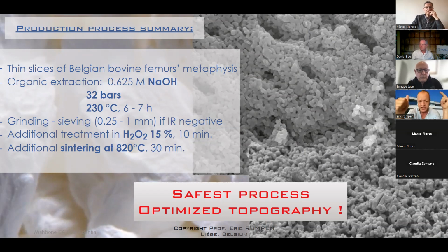So high pressure, high temperature in a soda solution for 6-7, sometimes 8 hours. Then the material is totally devoid of proteins. We have a grinding and sieving process, and then we add an additional treatment with hydrogen peroxide for 10 minutes. And then the additional sintering at 820 degrees for 30 minutes. That is the safest process with a very optimized topography.